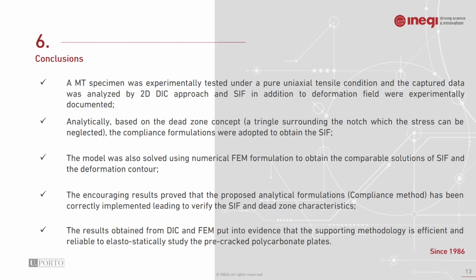The conclusion of this work can be stated as follows: the characteristic of the stress dead zone, and also the compliance function application on the stress intensity factor calculation, were used in order to prove the concept of the stress dead zone. A middle tension specimen made of polycarbonate was uniaxially tested, and digital image correlation was used in order to analyze the experimental data. The model was also solved using finite element method formulation in order to obtain a comparable solution on the stress intensity factor and also deformation.